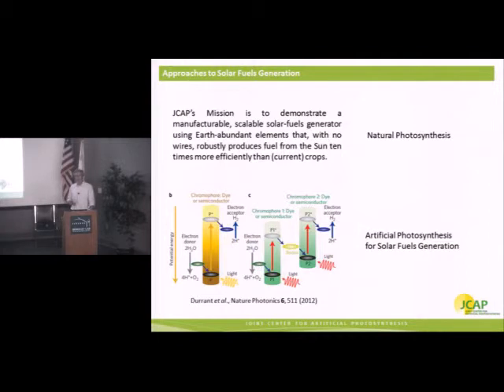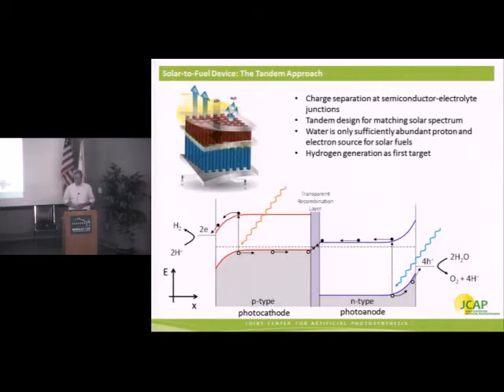That means that platinum, iridium, ruthenium, some of the best catalysts for doing these reactions, are automatically out. So we have projects within JCAP that are actively seeking to develop these new catalysts. And within our project, we're seeking ways to, with high degrees of efficiency, interface these to the semiconductor light absorbers without losing charge. Okay.